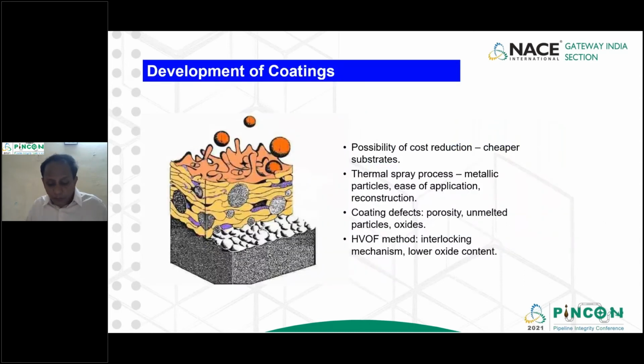Before I go into this experiment, I just want to talk about this coating, because the whole idea was with this particular alloy, nickel aluminum bronze, we took the cast metal. Then what is the need of this coating? The same composition I deposited on a mild steel substrate, so the whole idea was refurbishment, or maybe a cheaper alternative to the propeller base metal. So this is what I did, the coating.